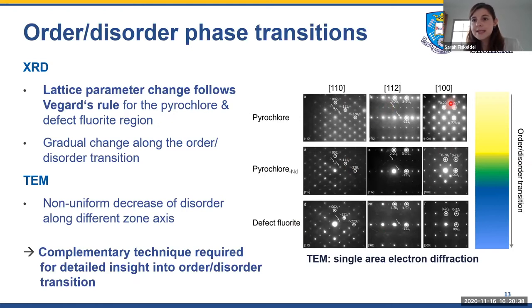And if we look along different zone axes, what we can see is that part of the superstructure reflexes which we see are still remaining in the defect fluorite structure, whereas along different zone axes, all the superstructure reflexes are gone for the defect fluorite structure. So there was an indication that there is some difference in the order-disorder transition at different length scales going on. So we were looking for a complementary technique to gain more insights into that.